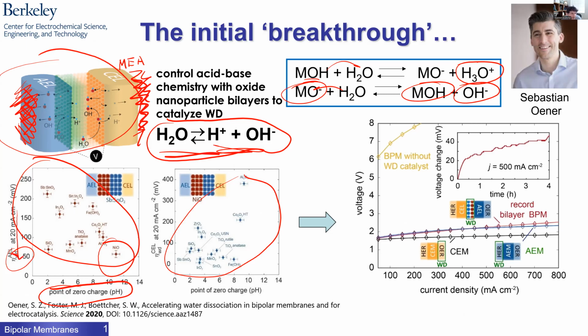So this is overpotential across this region. It's lower if the pH matches the local pH of the membrane that the catalyst is in contact with. So we developed these bilayer catalysts, where you want acidic metal oxides on the acidic layer. And you do this, and you can make really quite remarkably good bipolar membranes that dissociate water really fast.